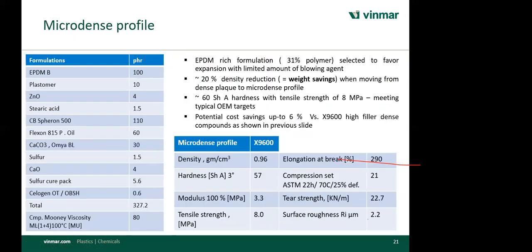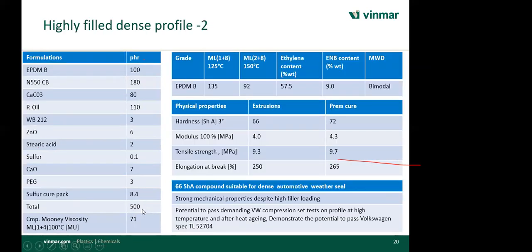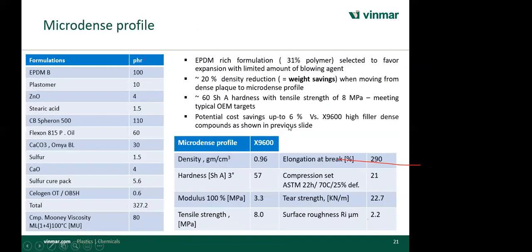Next is the microdense, the same EPDM polymer B that I have shown here. The technology is that you take a normal dense profile recipe and add 0.6 PHR of OT and or OBSH, like a blowing agent. What will happen? You will get micro sponge in your dense profile, so it will reduce the weight per meter. This compound has a PHR level of 327, and my last compound was 500 PHR, but this compound is still 6% cheaper than the first compound.